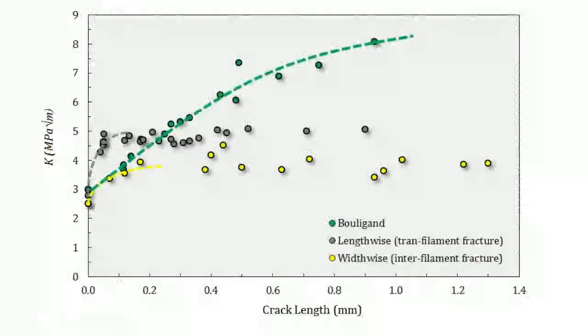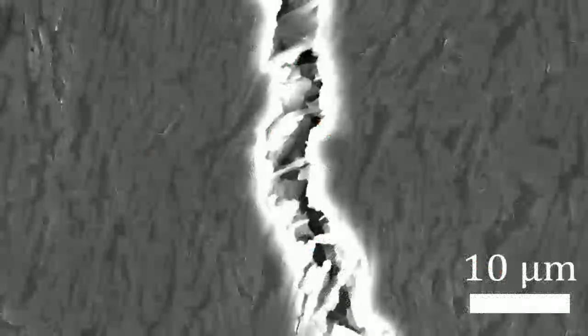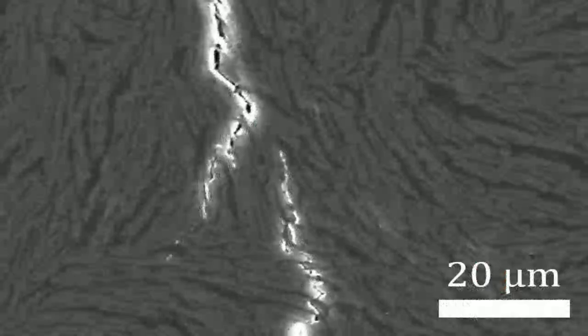They attempted some solutions, like trying to sinter at lower temperatures or applying a protective silicon carbide coating to the fibers beforehand. Did that work? According to the thesis findings, no, not really. These attempts weren't successful in preventing significant fiber degradation at temperatures still high enough to actually get the ceramic matrix properly densified. You couldn't get both.